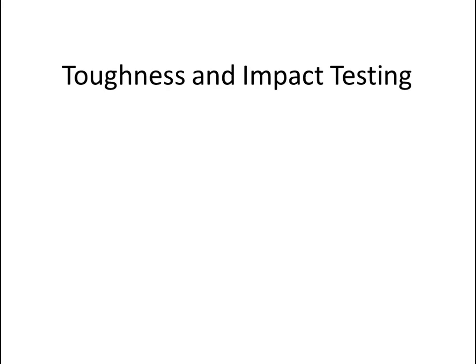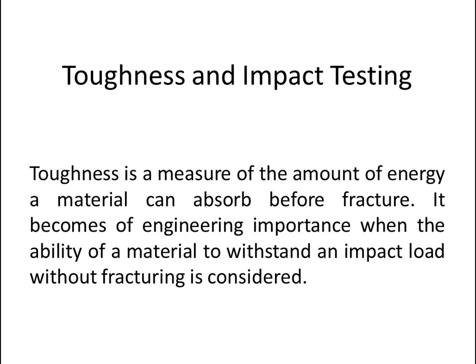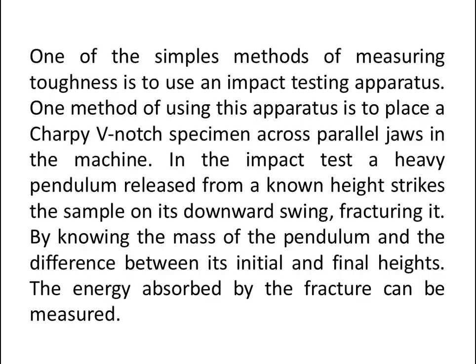Let's talk about toughness and impact testing. Toughness is a measure of the amount of energy a material can absorb before fracture. It becomes of engineering importance when the ability of a material to withstand an impact load without fracturing is considered. One of the simple methods of measuring toughness is to use an impact testing apparatus. One method is to place a Charpy V-notch specimen across parallel jaws in the machine. In the impact test, a heavy pendulum released from a known height strikes the sample on its downward swing, fracturing it.